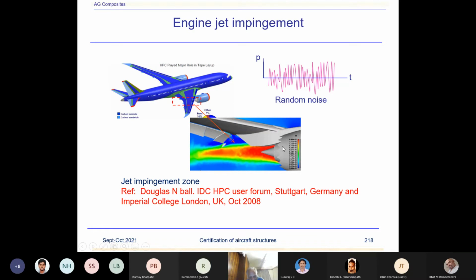And as you can see, this is the engine, and this is the flaperon. The 787 flaperon actually lies over here. So in this region, these parts are fairly close to this exhaust, and they become critical for the sonic fatigue. We had to investigate sonic fatigue compliance using the test data. I'll show you. So essentially, it's a random noise, low amplitude, high cycle, which could run into several millions over the lifetime of the aircraft.